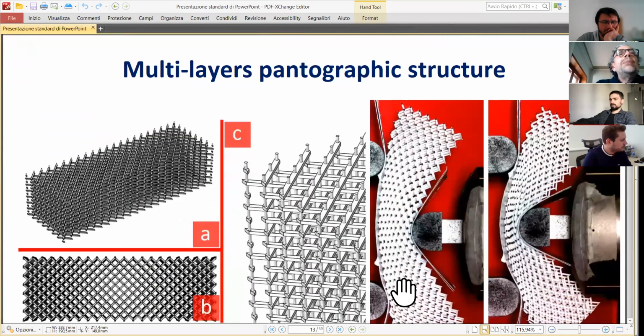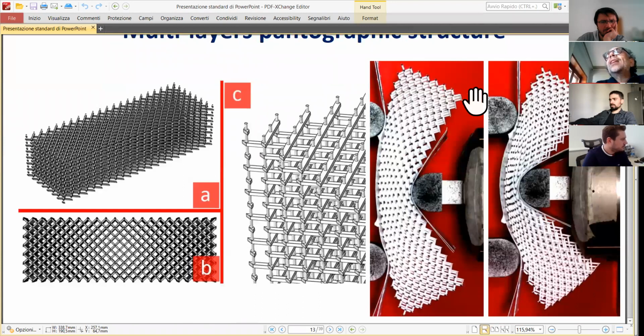Then we superimposed several layers of pantographic structures, and we have found that in a 3-point bending test, superimposed layers of pantographic structures have this very peculiar behavior. By the way, this deformation is fully elastic. If this moves up, the pantographic structure goes back to its original shape. And this effect can be very useful, for instance, in every damping device. And with Erden, we are trying to exploit this effect in a specific problem in mechanical engineering.